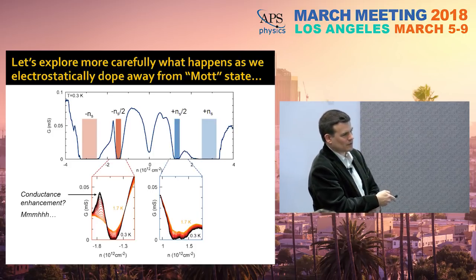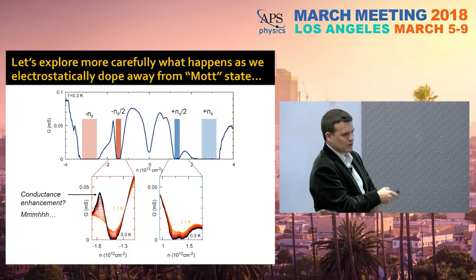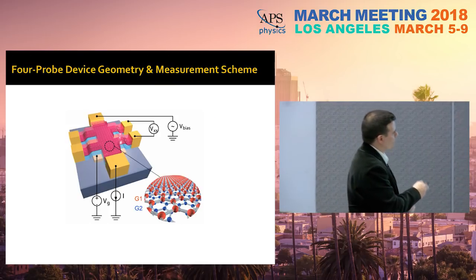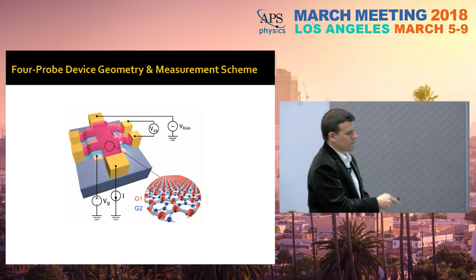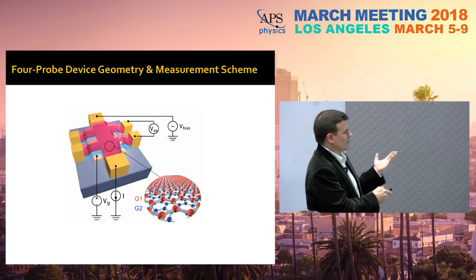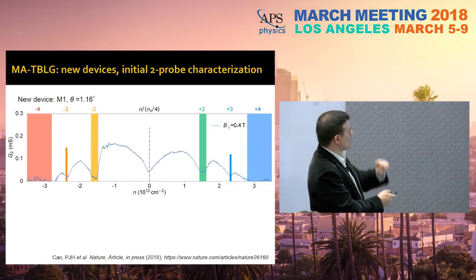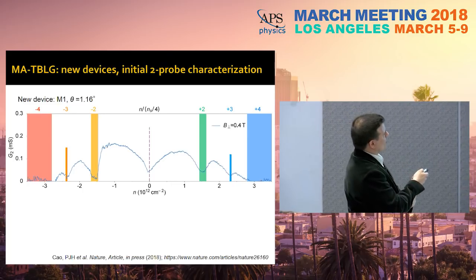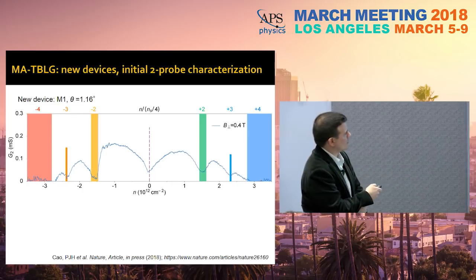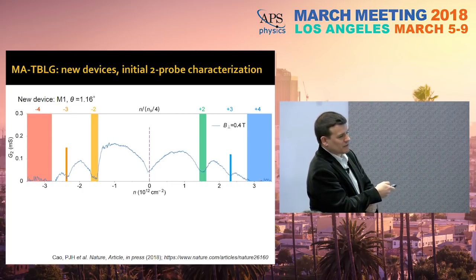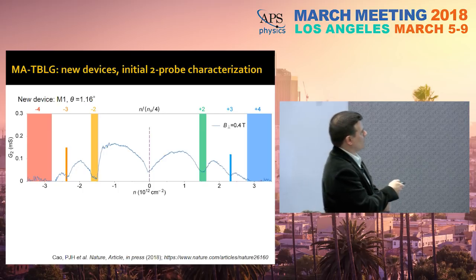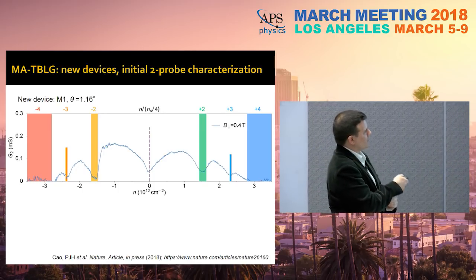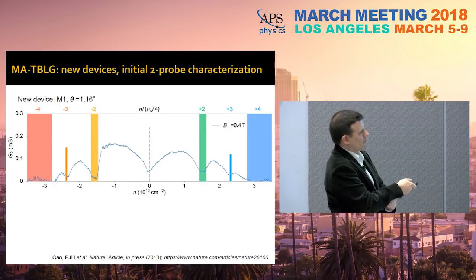These were two-terminal devices. So then I told my student, okay, let's make four-terminal devices. Let's look more carefully into this. So we made four-terminal devices. We first characterized them, again, in a two-terminal setting. This is another device, 1.16 degrees rotation angle. This is in the presence of a small perpendicular magnetic field, and you measure the conductance as a function of density. You have the charge neutrality, you have dips at 2, at 3, and at 4 electrons. Same thing, -2 and -3.